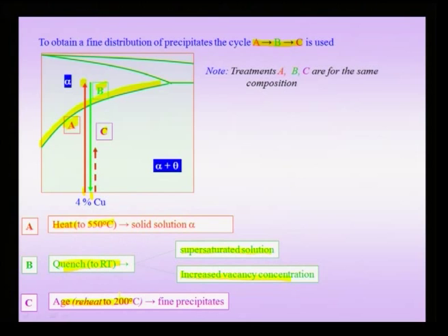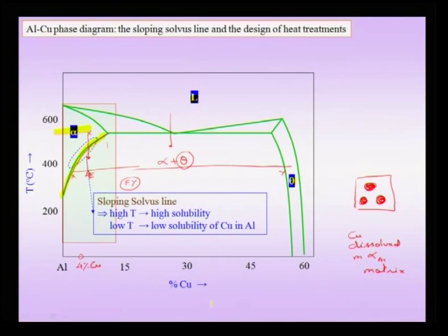that hardening took place, and what, as we pointed out, the micromechanisms involved are. And so, the third step we follow to get this fine precipitate is the aging treatment, in which case we heat to a low temperature. This temperature could be around 180 or 200 degrees Celsius, and this gives us fine precipitates inside the alpha matrix. So, let me summarize this slide, these three steps.